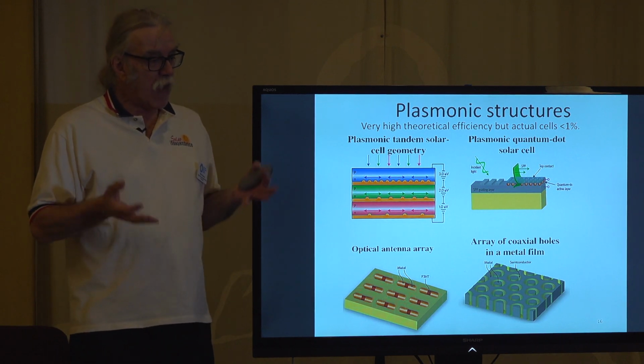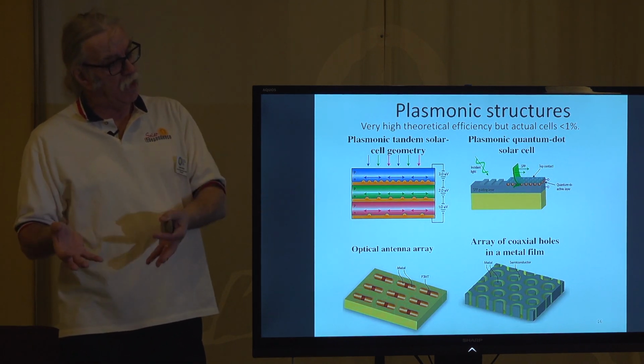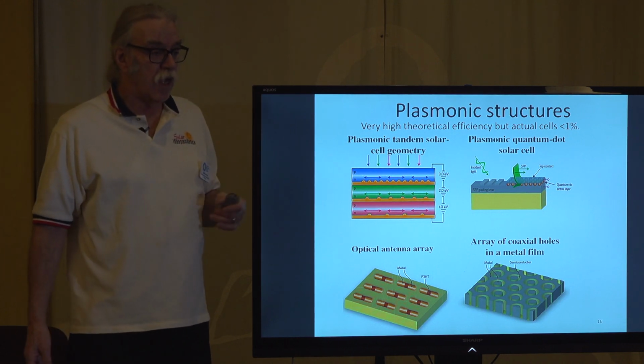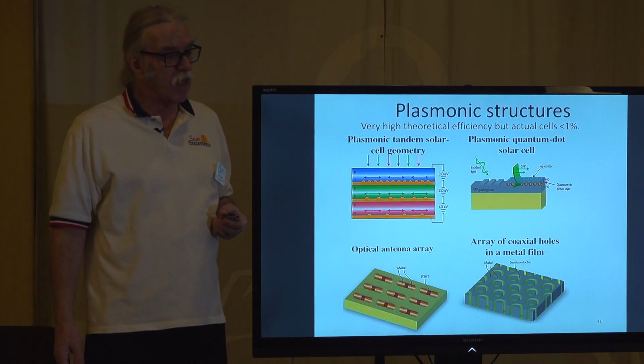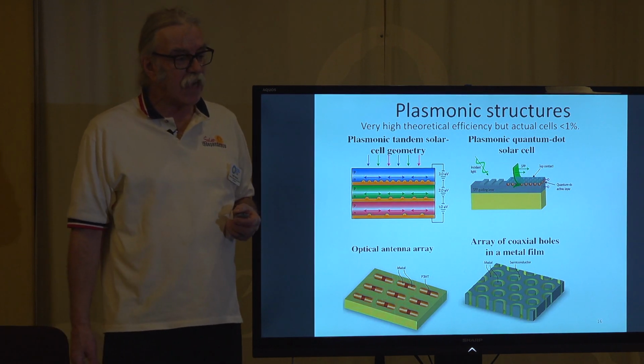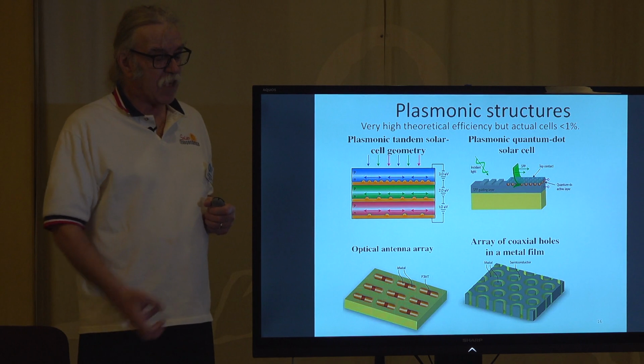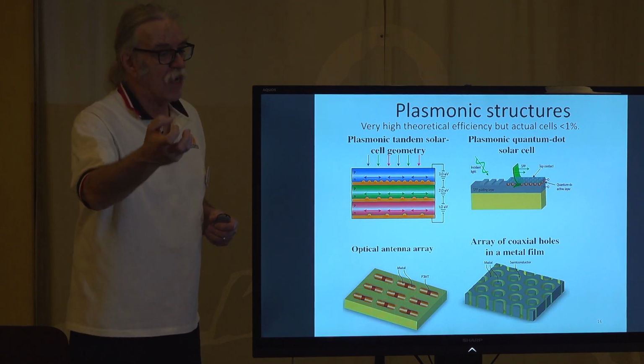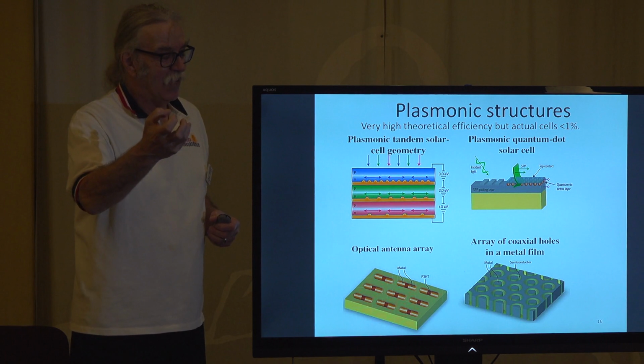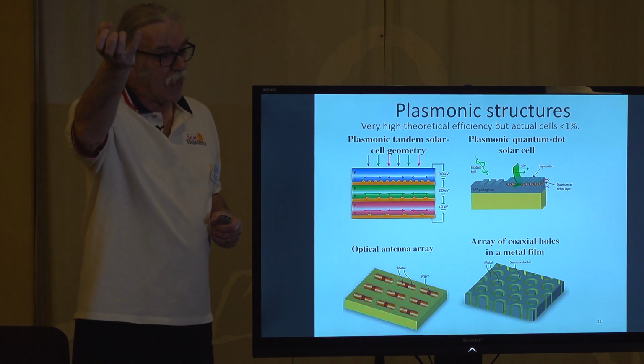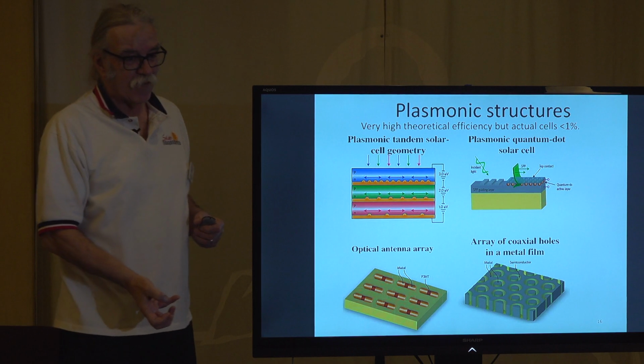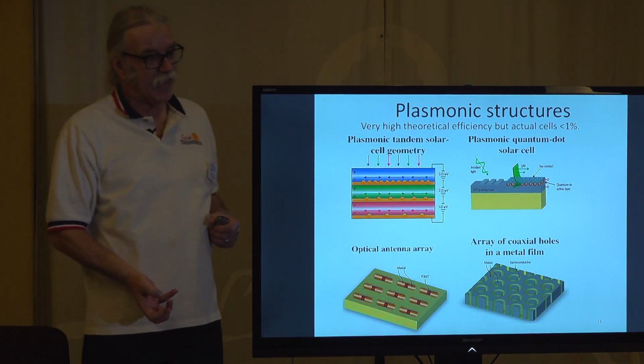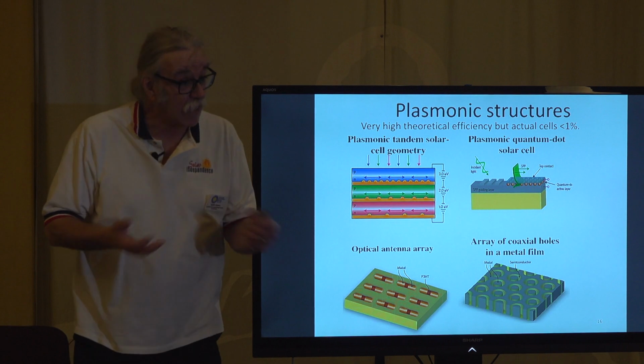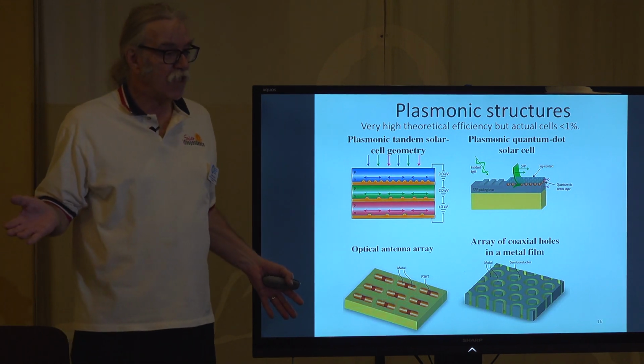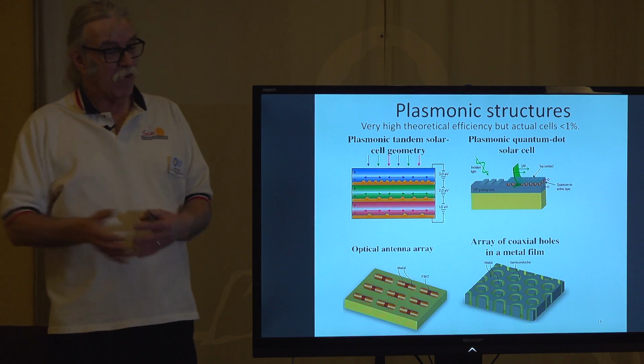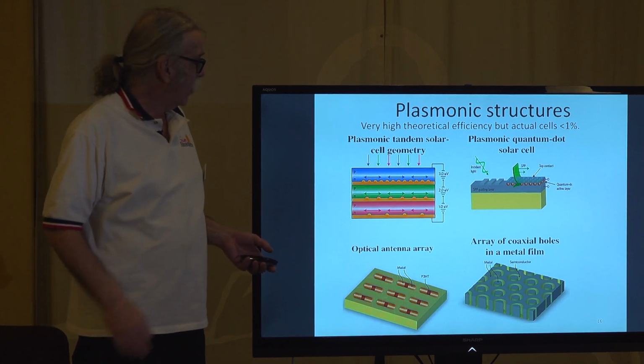And so the space guys want to know how much power I'm going to get at the end of the life. That technology may do it, but the space guys are incredibly conservative. And so they're not putting anything up for any satellite that means anything until somebody puts this material in space on a demonstration satellite where it doesn't have to work. Meaning they just put it up, they test it or not, and then they bring it back down to the Earth, and if it survived, it's good. Most thin films haven't passed that test, by the way. Because of the thermal cycling, that tends to rip packages apart, minus 40 degrees C, plus 90 degrees C, every 90 minutes, and things like that are really rough.